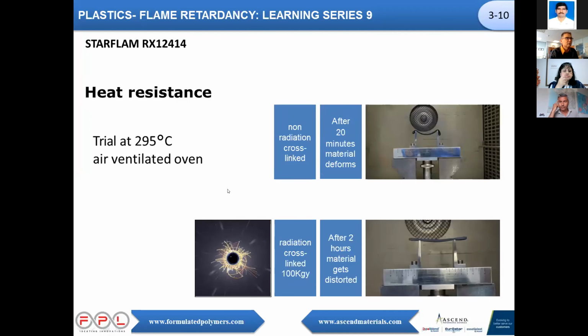If you take the same material, cross-linkable, what do you see? If the material is cross-linkable but not cross-linked, you see that it already reacts, meaning that after 20 minutes, the material gets deformed, but it's no more in liquid form, meaning that already with the additive we place in, there is a reaction to heat. But if you cross-link the material at 100 kilogray, even after 2 hours, the material gets distorted but maintains its shape. And this finds a lot of application, and it's really a clue that the material can withstand high heat for some time.